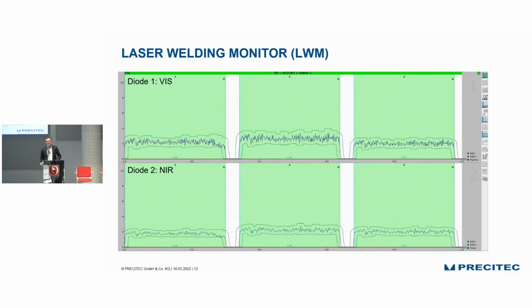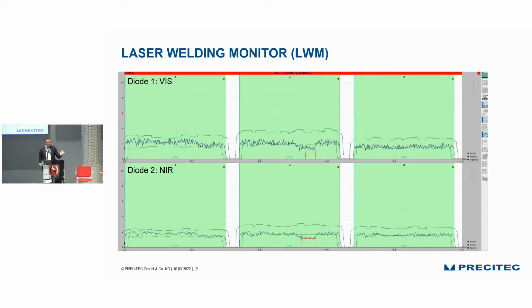Now, seeing this sensor in action can be seen in this video here. At first you can see the photodiode which is sensitive in the visible range of light, and second the photodiode which is sensitive in the near infrared. And if the current sensor signal, highlighted here in blue, is between the limits, the envelopes, then we say it's a good weld. If it was found to be outside the limits, as shown here, then we give information to the PLC in real time saying, pay attention, there was something wrong. So a system and a sensor based on comparison.